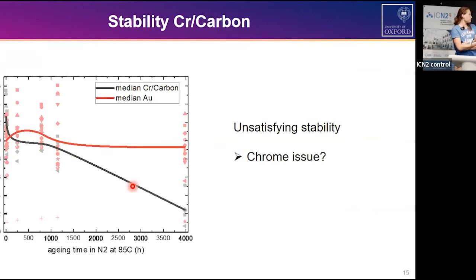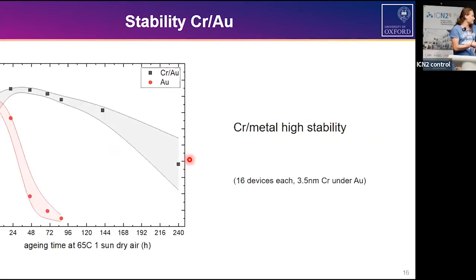Even in a longer study, this is also in nitrogen, extending what I showed in the last slide, the chrome carbon is less stable than gold. So for PIN carbon, it was a first really disappointing result that it's not beating gold in stability. We first saw the chrome being the issue, but then it didn't look like the chrome as material was an issue, because when we compared metal electrodes with a chrome layer and without a chrome layer, it looked like it made it even more stable. So at least no disadvantage out of it.